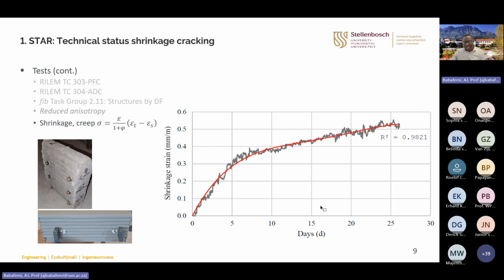And we can investigate that in certain 3D printed hollow plastic molds as shown in these figures. And then we can apply an LVDT to measure the shrinkage over time.